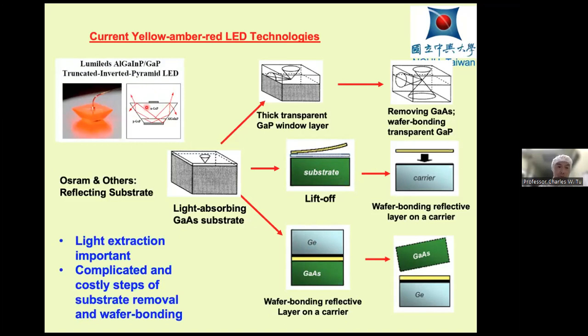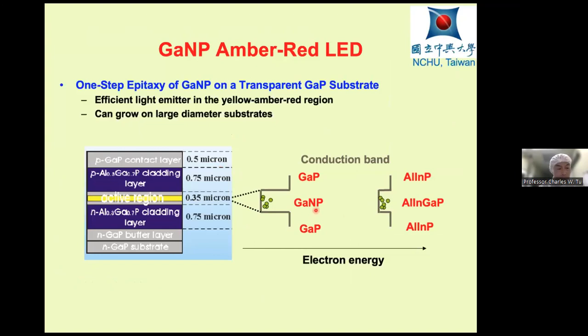So light extraction is important, but you can see all this involves substrate removal because the gallium arsenide absorbs this red, short wavelength light. But now we have nitrogen in gallium phosphide. Gallium phosphide is an indirect bandgap and a large bandgap, so it's transparent. And so we can make this with one-step epitaxy onto a transparent gallium phosphide substrate. In principle, we can eliminate the wafer bonding process, and so it should be cheaper.